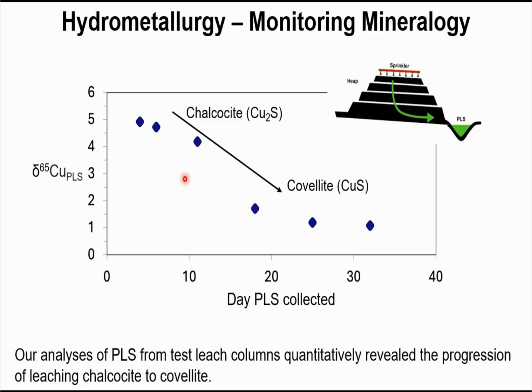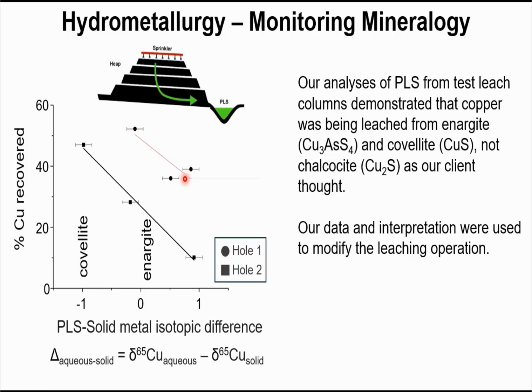So we've done this now to monitor mineralogy in a heap leach operation. Just by measuring PLS, we can tell you you're leaching chalcocite. Just by measuring PLS, we can tell you you're leaching covellite. We did work recently for one client where they thought they were leaching chalcocite, but we were able to use the metal isotope, in this case copper isotope composition of PLS, to tell them they were actually leaching covellite and enargite, not chalcocite. So they could change the composition of the lixiviant to increase the recovery of copper.